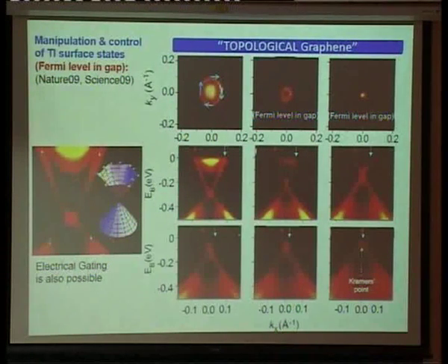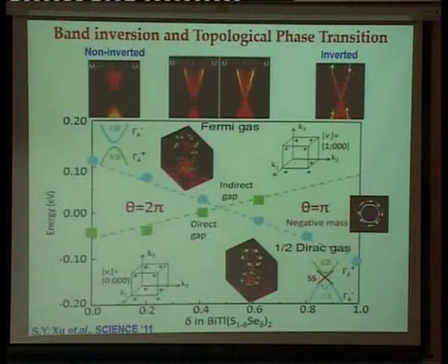You can manipulate these surface states under UHV. It's not easy to do transport under UHV, but you can get your Fermi level in the gap and maintain it there and do all sorts of measurements under UHV, and for spectroscopy, that's fine. And so that's what we are doing.